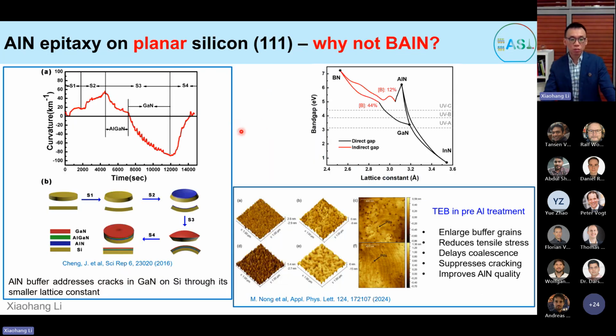Typically, as you well know, people have developed the aluminum nitride buffer to grow crack-free GaN on silicon. Why aluminum nitride? Because aluminum nitride has a smaller lattice constant compared to GaN. So by having aluminum nitride as a buffer, you can provide sufficient compressive strain so that you prevent crack formation on GaN on silicon. However, for aluminum nitride, if you look at this indium aluminum gallium nitride system, there is no material with a smaller lattice constant than aluminum nitride.